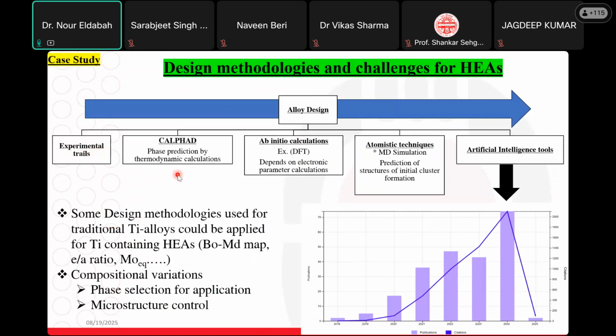Many simulation techniques and the calculation of phase diagram, like Thermo-Calc and similar softwares, will help you to make a phase prediction. But actually, for a newly introduced category, if you are going to use thermodynamic calculation, this needs some experimental validation to be acceptable. The phase diagram obtained by thermodynamic calculation or softwares needs to be verified first, because in some cases we may face some foreign phases inside our alloy, but this is not identified by the thermodynamic calculation. So experimental validation is required for using calculated phase diagrams. Other techniques include ab initio calculation or atomistic techniques.